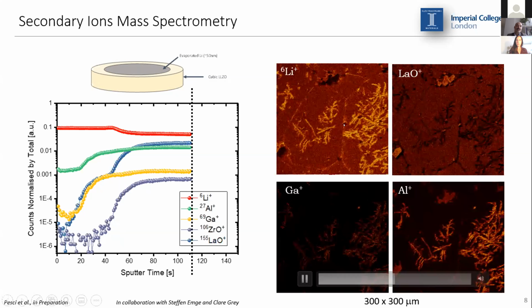If we look at the high-resolution images, we can clearly see information on the chemical composition of grain boundaries, which, for instance, appear to be rich in lithium and aluminium, but perhaps depleted in lanthanum. Or we can see the presence of secondary phases, this lanthanum aluminate here. In this region, we have an enrichment of these two elements, but a depletion of lithium. So this is just to show you how powerful SIMS can be to study lithium-containing materials.